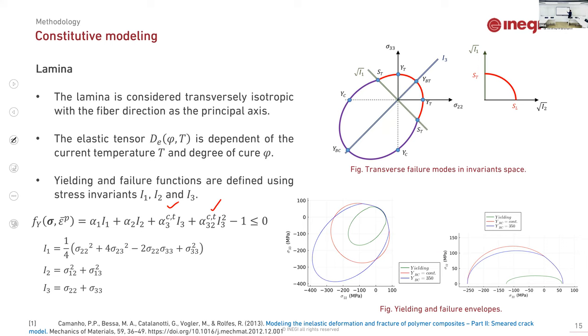We perform a lot of experimental tests to characterize transverse tension, shear, and compression. These are complex to measure, but they could be approximated. So we can define these failure envelopes. There are some examples for the material that I am using. This curve corresponds to the failure, and this green curve corresponds to the yielding surface. This is in the plane 2-3, and this is in the plane shear 1-2, axial stress 2-2.